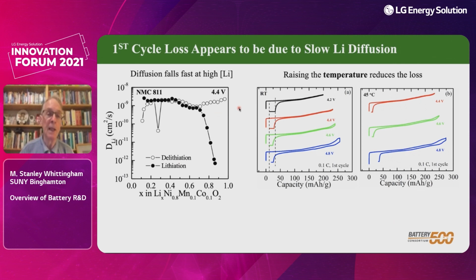And we clearly speculated that this was related to diffusion. And what we found out is that diffusion falls very fast at very high lithium contents. So up to about 70%, 75% lithium contents, it's about 10 to the minus 9. As soon as you go above that, it drops by 3 orders of magnitude. And this is due to the diffusion mechanism, which is a divacancy mechanism. So for every ion to jump, you need 2 vacancies next to that ion. And you can look at this as if you look at a lecture hall. The lecture hall is 75% of the seats are full.